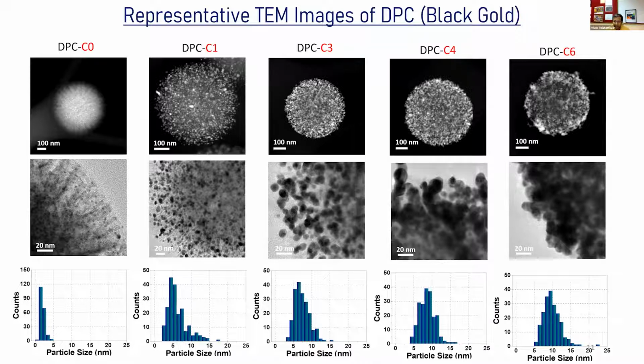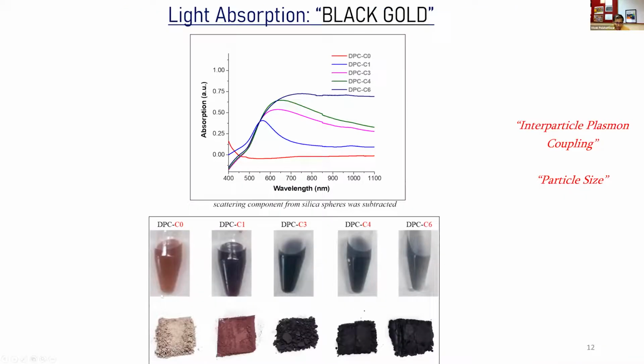So that's why we prepared a range of these materials, and then we try to study them for light absorption behavior first. And now you can see this is C0, C1. Typically, just looking at them by your eyes, you can see now the color changed, and you got black color gold. So it's still a gold, metallic gold, no change in the oxidation state, no doping, no functionalization.